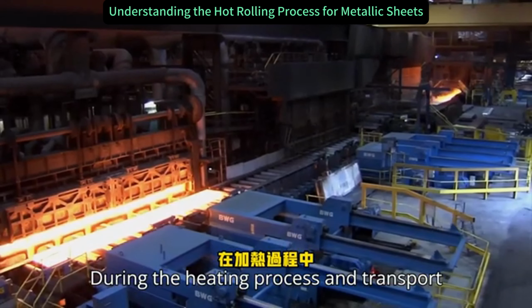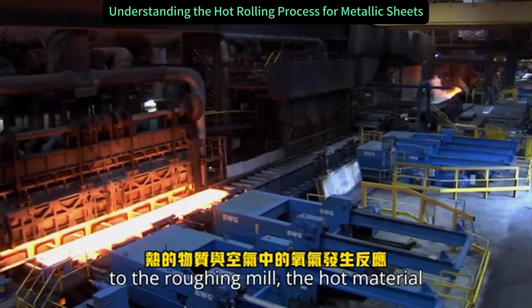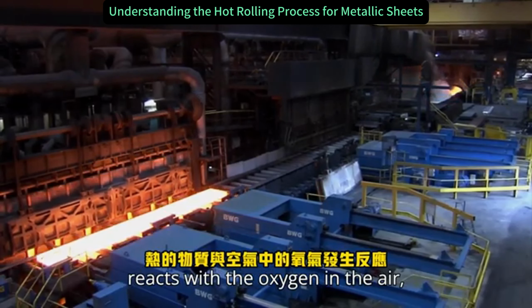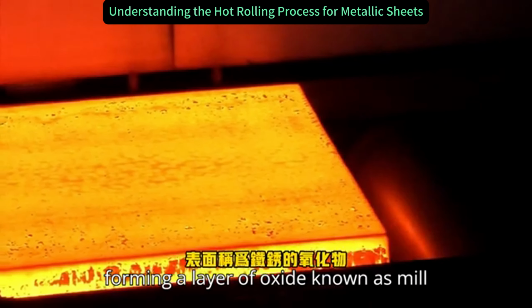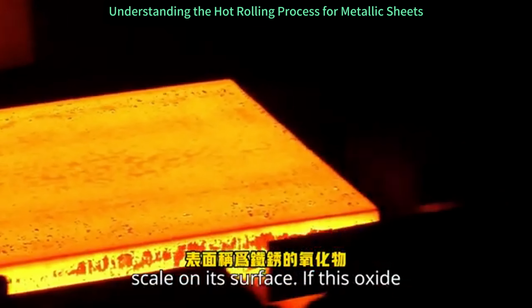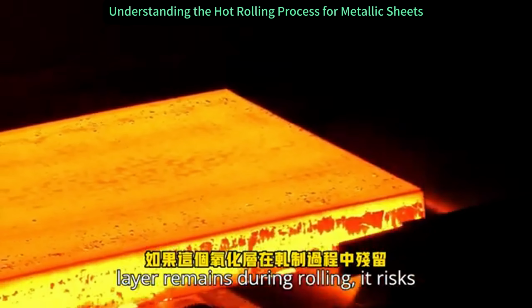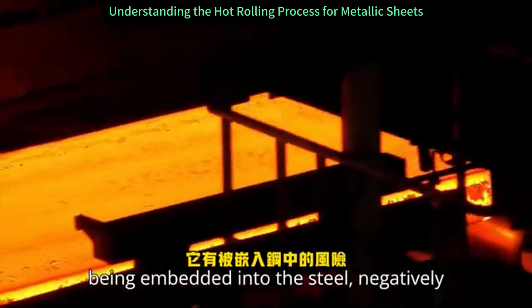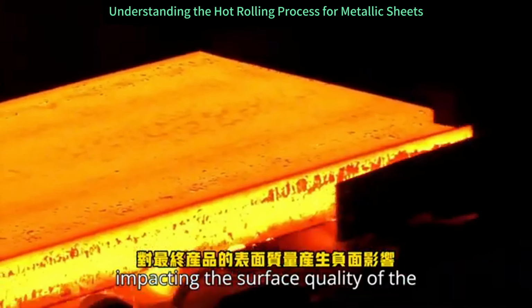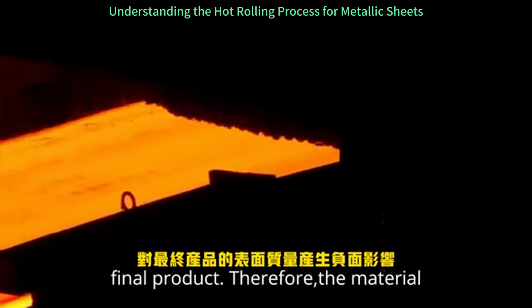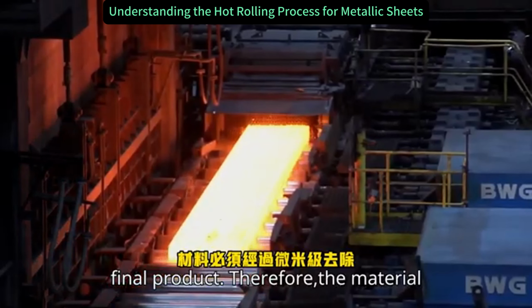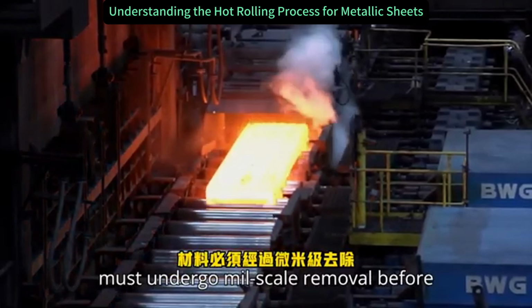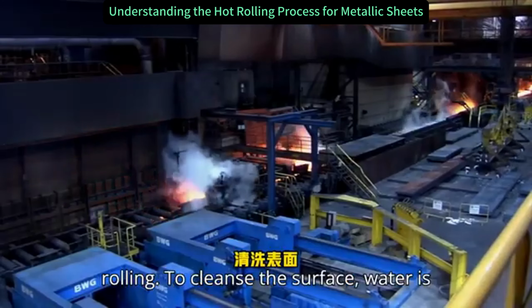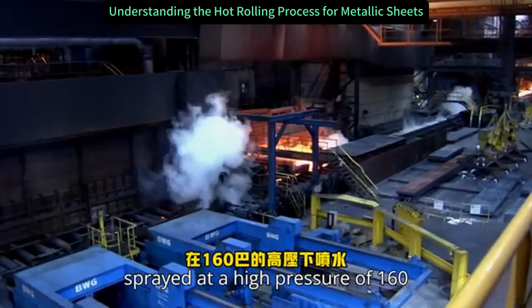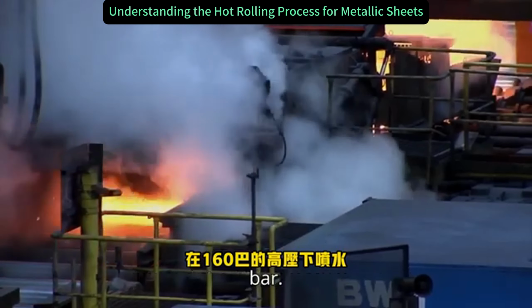During the heating process and transport to the roughing mill, the hot material reacts with the oxygen in the air, forming a layer of oxide known as mill scale on its surface. If this oxide layer remains during rolling, it risks being embedded into the steel, negatively impacting the surface quality of the final product. Therefore, the material must undergo mill scale removal before rolling. To cleanse the surface, water is sprayed at a high pressure of 160 bar.